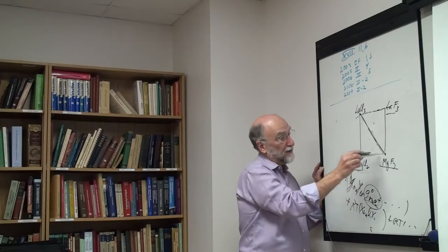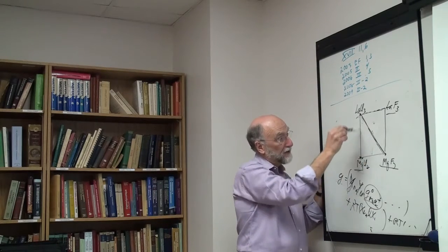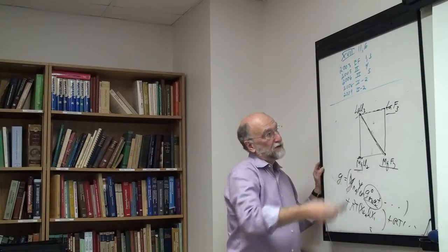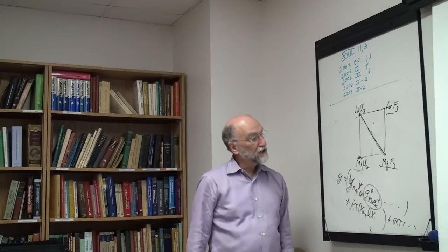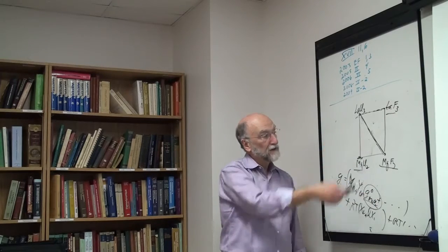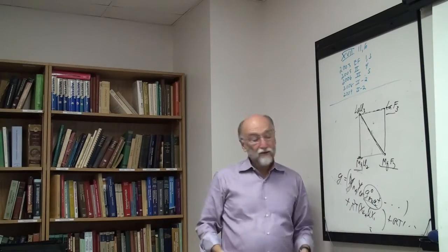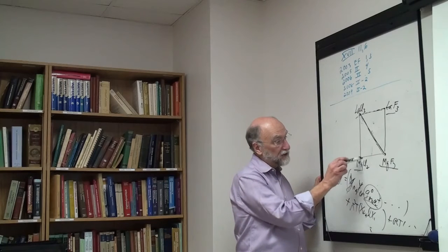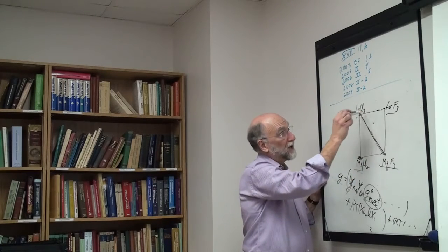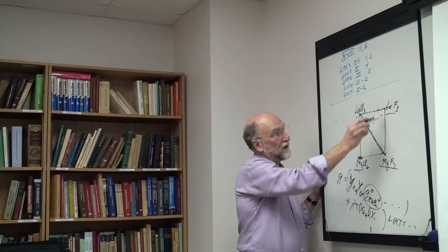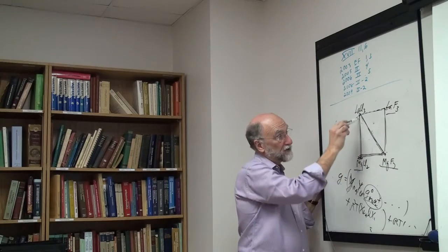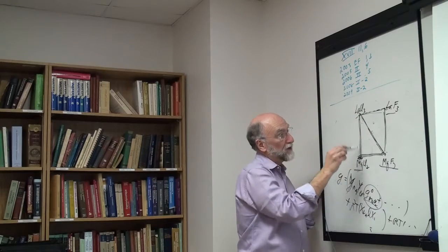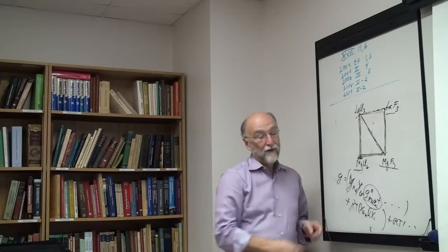The binary systems, all these binary systems here, can be simple eutectic systems, but if your delta G exchange is very positive or negative, you're going to get all sorts of deviations in the ternary. So you need the delta G of exchange for all the phases, you need the Gibbs energies of all 4 corners, and you need the phase diagrams of all 4 binary systems, not just this and this, but this and this as well.